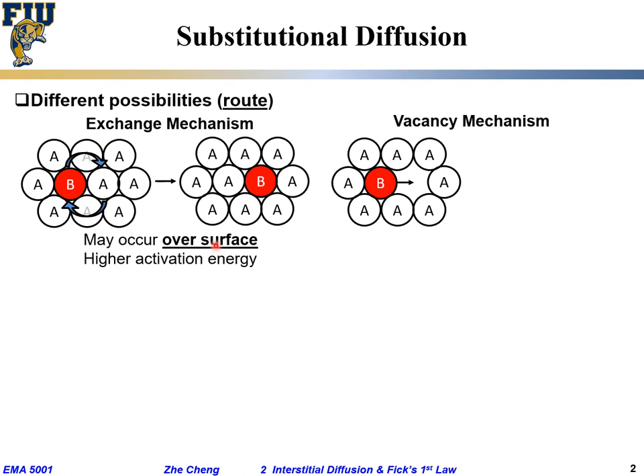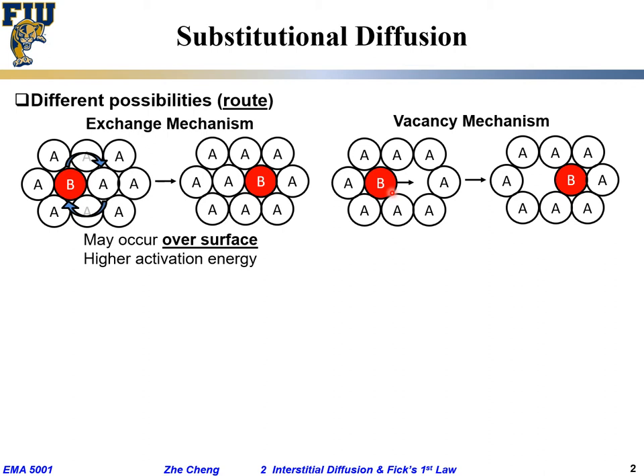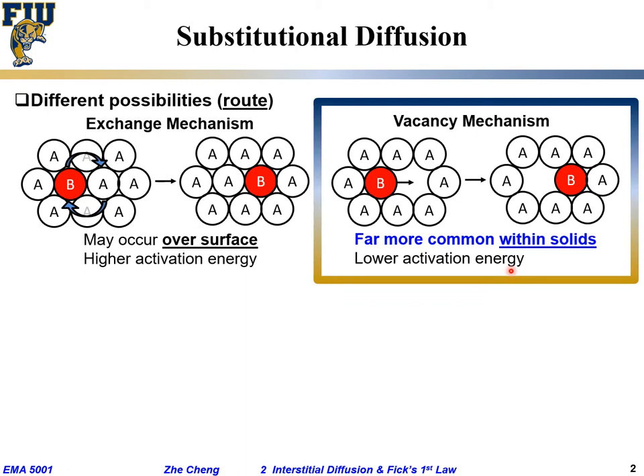Another so-called mechanism, or route, is the vacancy mechanism. Vacancy means a missing atom. We have A and B atoms together, and the B sits here, and let's say at any moment I have a missing atom near B. Then naturally, at the next moment, where would this B go? Of course, just by probability, it goes to the neighboring vacant position, right? This is so-called way more common. It happens within solids, and compared with the exchange mechanism, it needs much lower activation energy. This would be the predominant way for so-called substitutional diffusion.